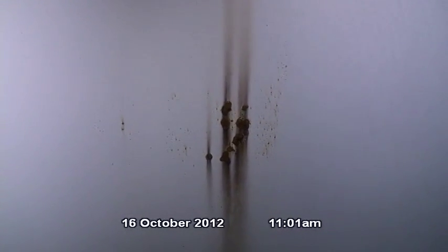We're continuing to document the condition of the epoxy coating on ring number 3. A large area of both pinhole type corrosion and light to moderate corrosion is present on the shell in this area. The diver has now reached the weld that connects ring number 3 with ring number 4. Pinhole type corrosion is present in a couple of areas on the weld. The diver inspector is continuing to move clockwise.